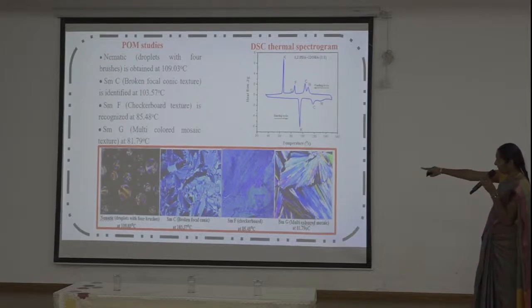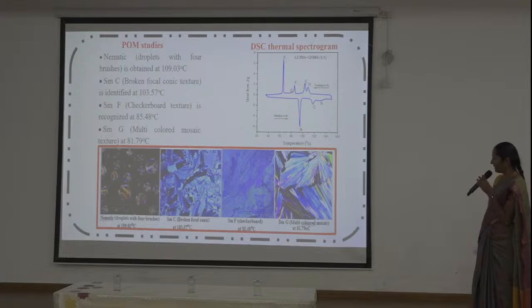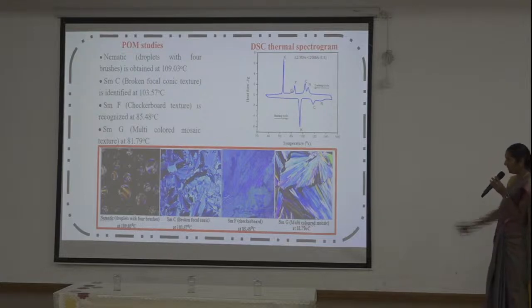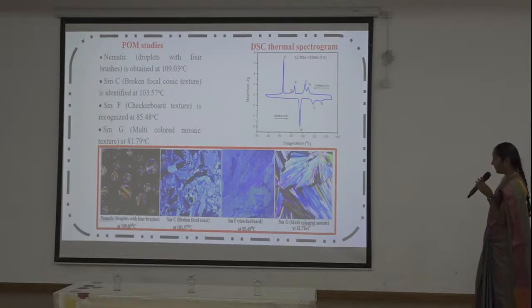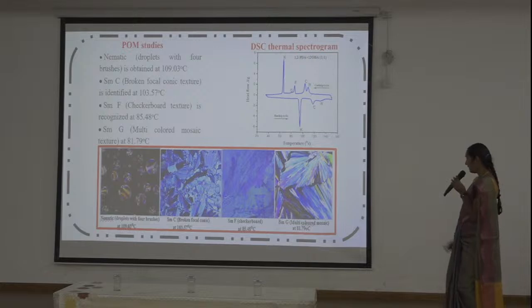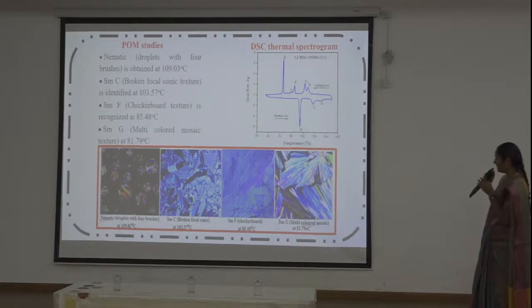After that, while gradually decreasing the temperature, I found Smectic C. This type of structure is called the broken focal conic structure, observed at 103.57 degrees centigrade.